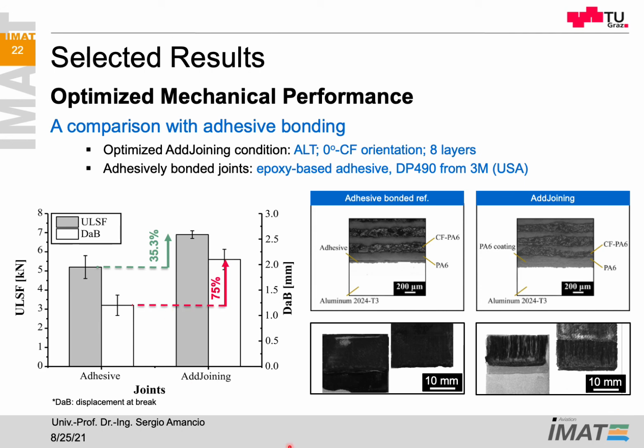And this can also be better understood if you look at the tested specimens. In dark is the adhesive here. This is the metal side, this is the metal side, and what you see is that the failure took place between the adhesive and the 3D printed composite parts. That led to an adhesive failure, reducing the mechanical resistance, while in the case of the AddJoints, the failure didn't take place in the coating layer and the first printed layer, but as we published in other papers, this fracture takes place between the first layer of carbon reinforced composite and the unreinforced composite. So it is a failure in the composite part, a cohesive failure in the composite part. That explains the better mechanical performance.